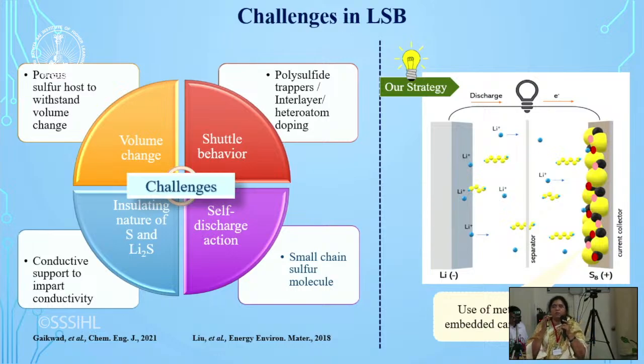So you have to keep this sulfur inside the carbon. So what we have done is we have modified or embedded metal nanoparticles onto this carbon. These work as electrocatalysts, and these electrocatalysts see that the shuttle effect is minimized and you can have better cycle life. And the last one is to use directly small chain sulfur molecule. So this also addresses the shuttle effect to an extent, and you can have longer cycle life.